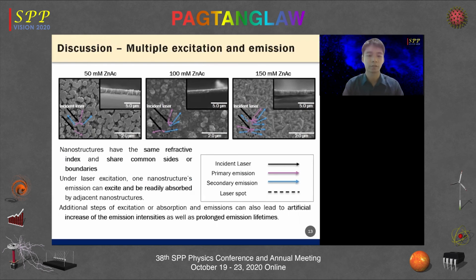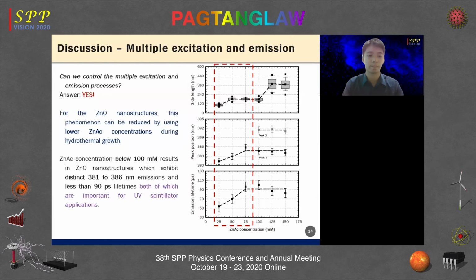Nanostructures have the same refractive index and share common sides or boundaries. Under laser excitation, one nanostructure's emission can excite and be readily absorbed by adjacent nanostructures. Additional steps of excitation or absorption and emissions can lead to artificial increase of the emission intensities as well as prolonged emission lifetimes. More importantly, for our zinc oxide nanostructures, this phenomenon can be reduced by using lower zinc acetate